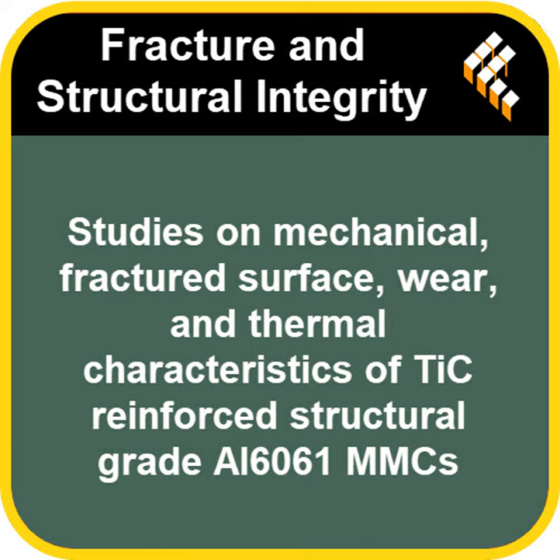The paper suggests factors like increased surface roughness at higher TiC content could lead to higher internal friction. And the TiC particles themselves might act as abrasives internally at these high concentrations, increasing friction and wear within the material structure, which contributes to more expansion. Micrographic research also suggested that reinforcing aggregation and clustering became more prominent along with that increased CTE value. So it all points back to too much TiC causing structural issues. It's remarkable how consistent that finding is across mechanical and thermal properties.